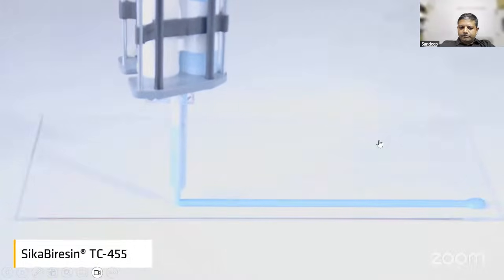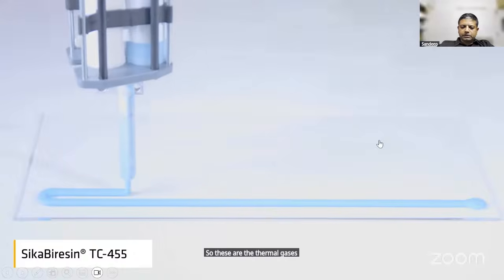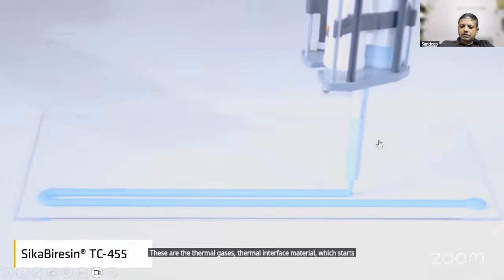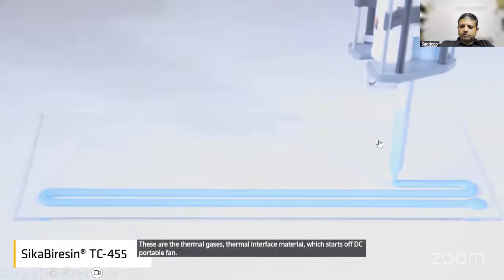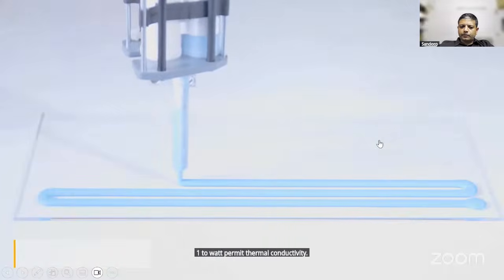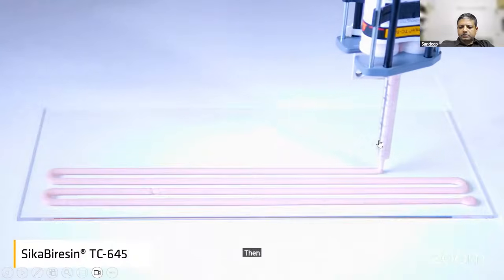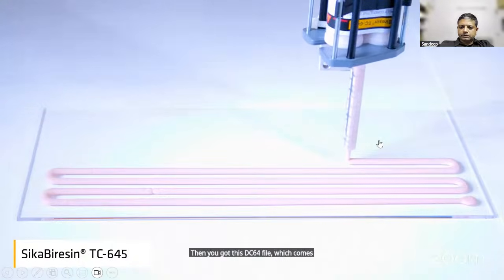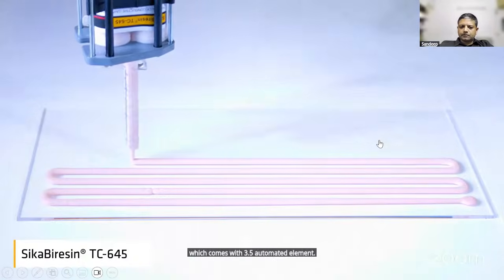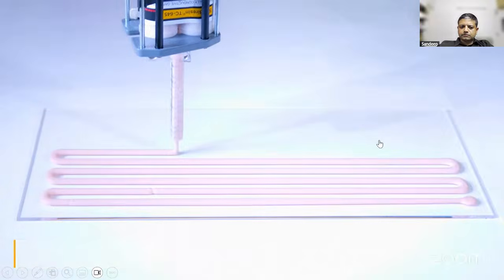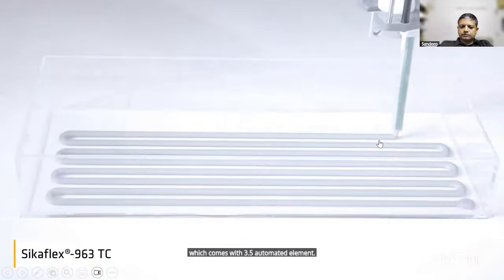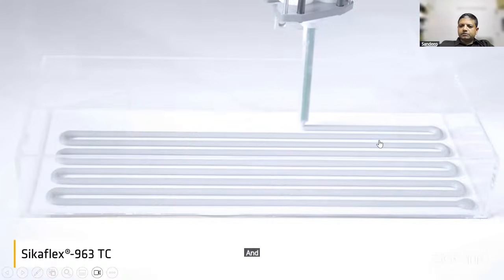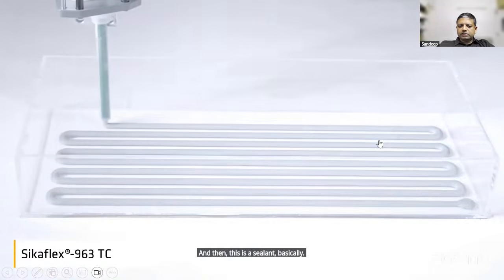These are the thermal interface materials. It starts with TC455, with 2.2 watt per meter Kelvin thermal conductivity. Then you have this TC645, which comes to 3.5 watt per meter Kelvin. And then this is a sealant, basically Sikaflex-963 TC.